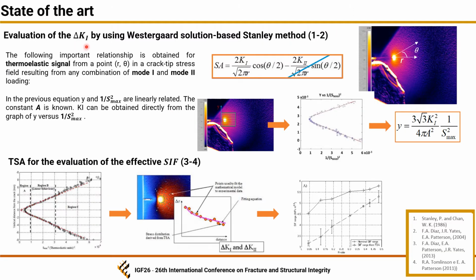Stress intensity factor is used for describing the stress state and then the mechanical behavior of the material in the presence of cracks, and it can be experimentally assessed using a contactless technique such as the thermoelastic stress analysis technique. Stanley presented, for example, a procedure based on the Westergaard equation for the elastic plane stress condition. In this case, the stress intensity factor can be obtained by relating the first stress invariant and the crack tip position, and the main advantage